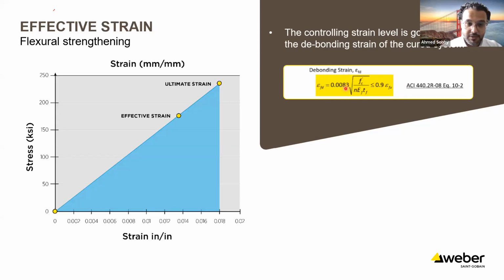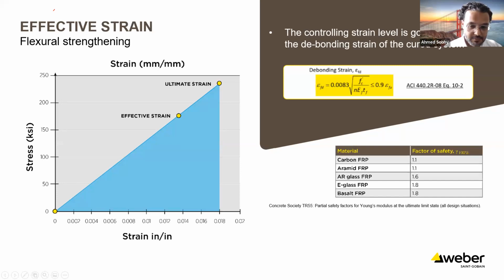As we can see from the equation in here, this is to calculate the debonding strain or the effective strain. And as we increase the modulus of elasticity, as we increase more layers, as we can see in here, we decrease the effective strain or the debonding strain. So as we add more layers, we get literally marginal increased capacity. And this is why it's important to note that adding plates and plates over plates over plates is not the answer to increasing the structural capacity in flexural strengthening.